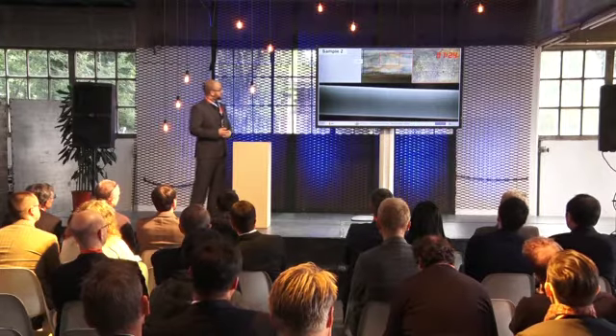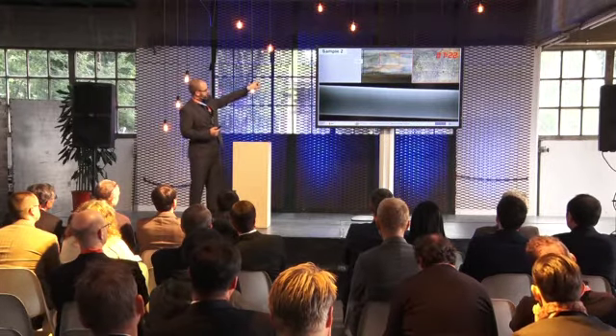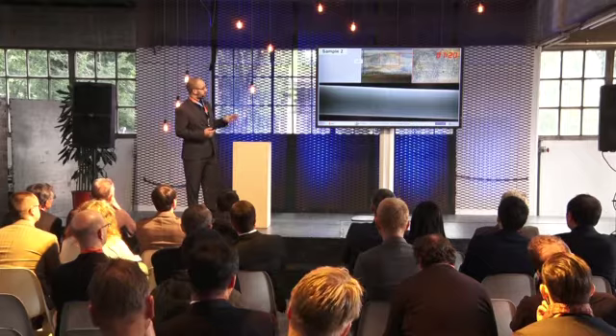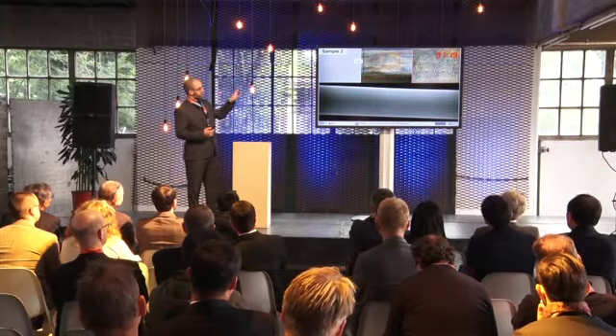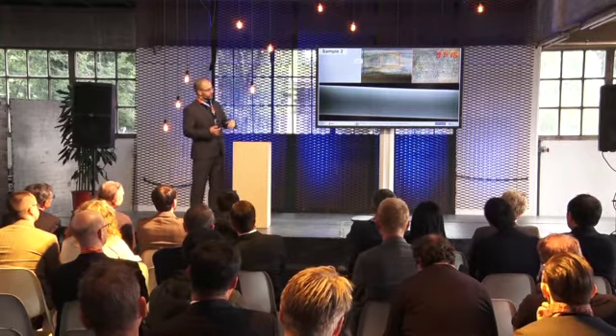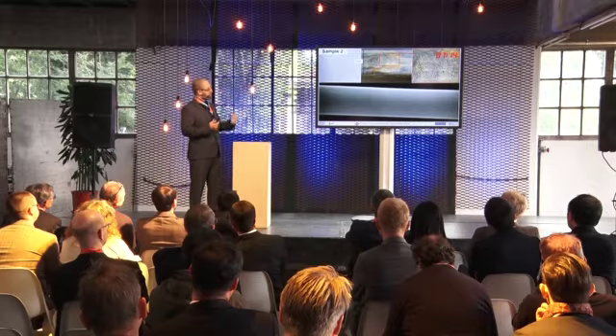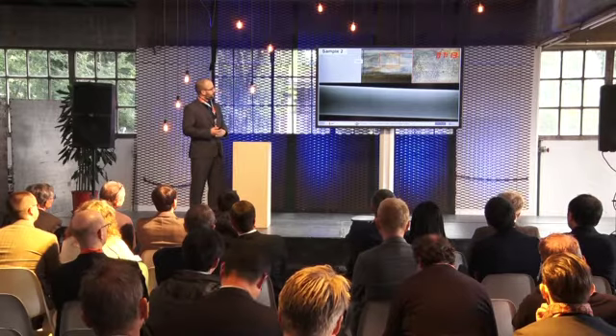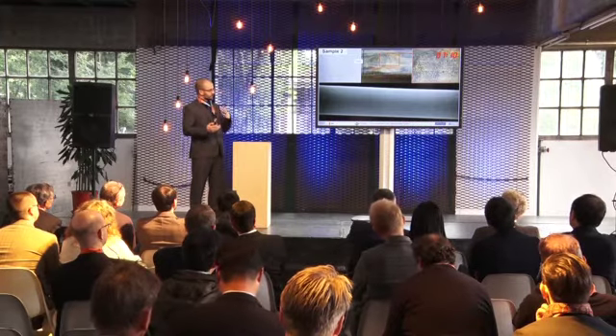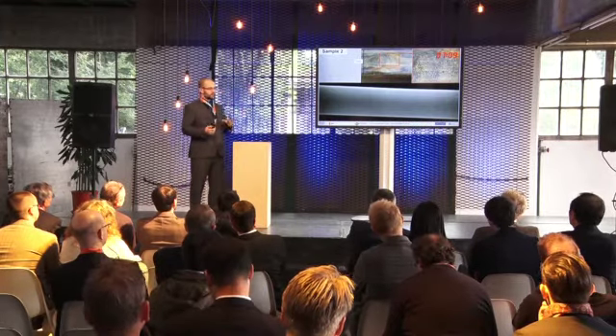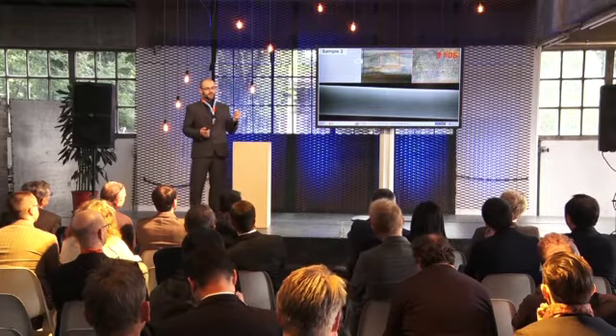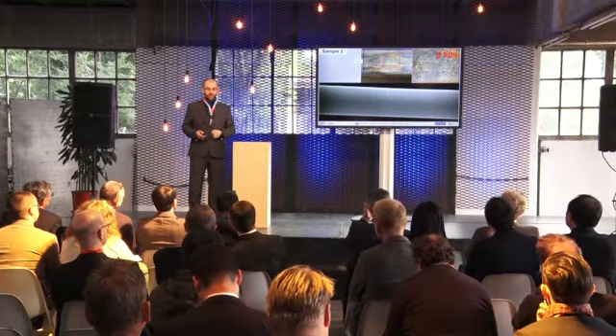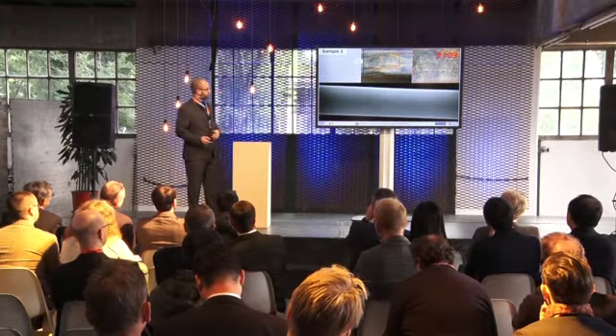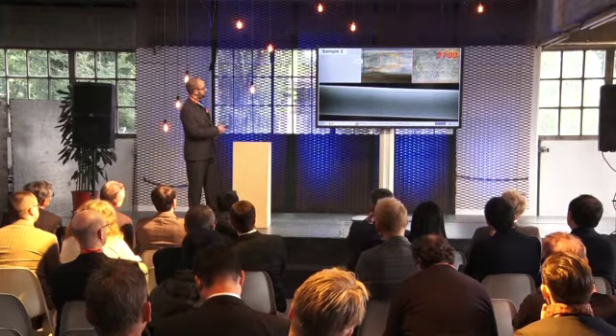And just as a finishing note, this is just showing how the surface of this rail, both within the defect and outside the defect, is showing localized lamination. There's some grinding marks as well, and it's work in progress, but I'm currently looking at linking the surface damage to areas of very high damage subsurface. So again, showing the importance of good quality surface finish.